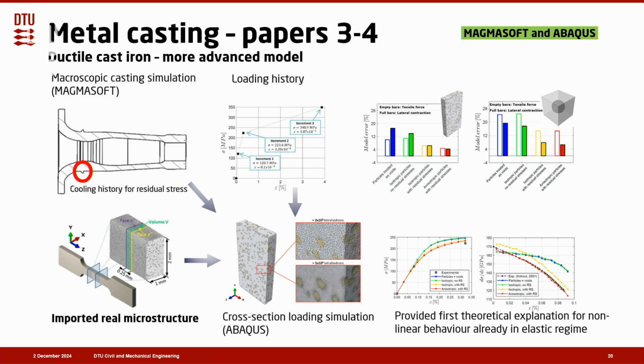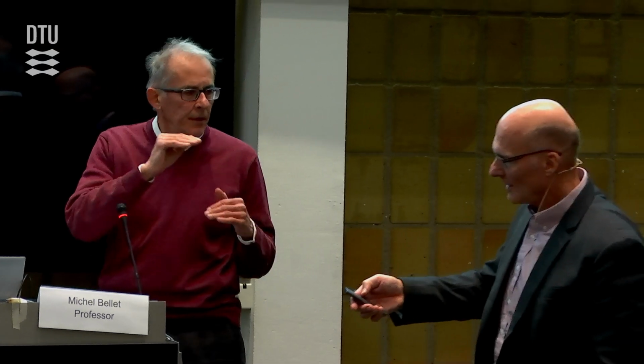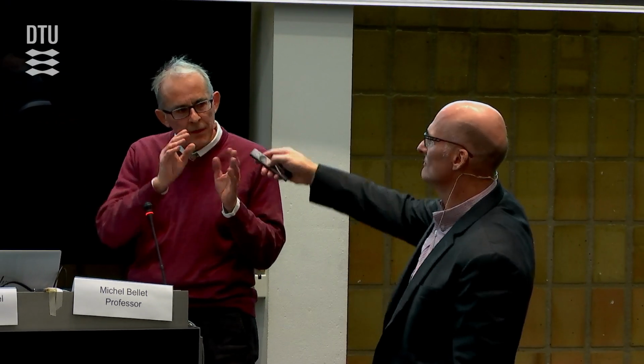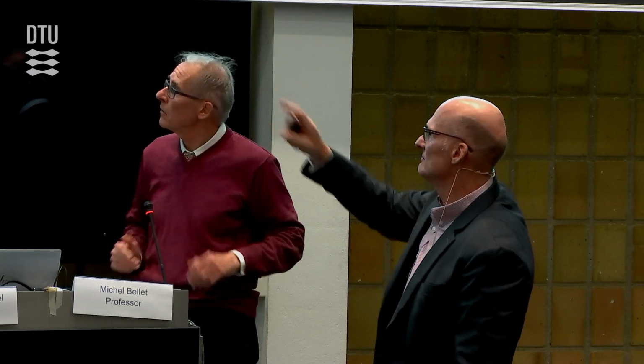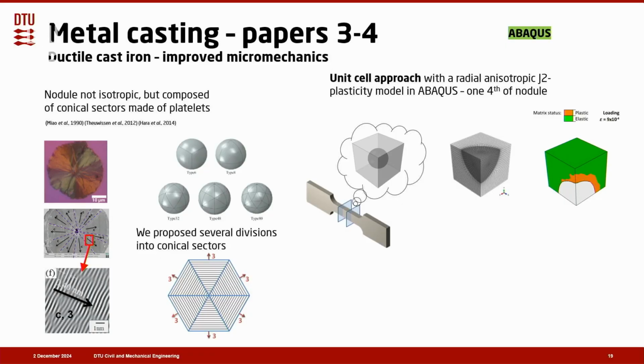And this is also what we can see down here, the red curve, especially the curve to the right, the red curve with the triangles. That's anisotropic with RS, with residual stresses. So it's a combination of the two, because when you assume that they are anisotropic, you actually calculate the residual stresses more realistically, so that when it's loaded, it reacts. So the anisotropy coming from the structure in platelets of graphite. Yes. In each sector of a nodule. Yes, exactly. Okay, very good.